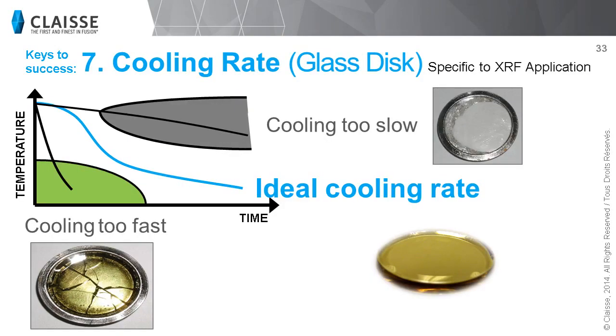In order to obtain a stable glass disc, your cooling step must be well controlled. Remember that when preparing a sample by borate fusion for XRF application, the temperature of the lithium borate melt with your sample dissolved into it is around 1000 to 1100 Celsius degrees. You then cast it into a preheated platinum gold mold and you cool it down.